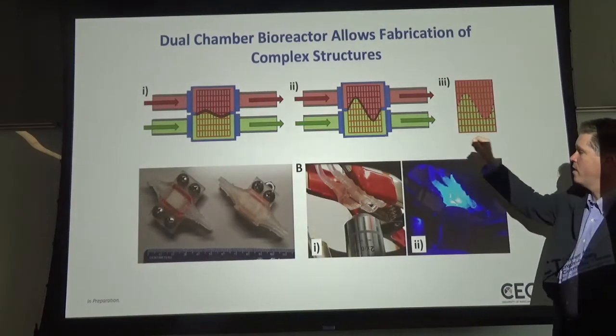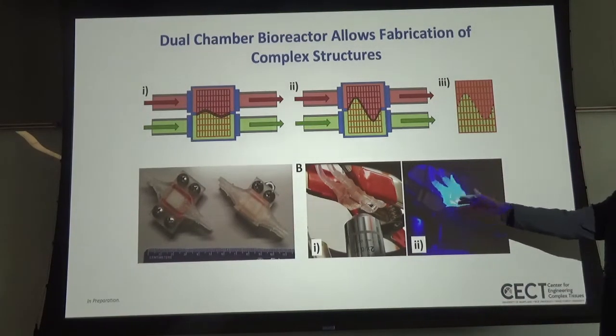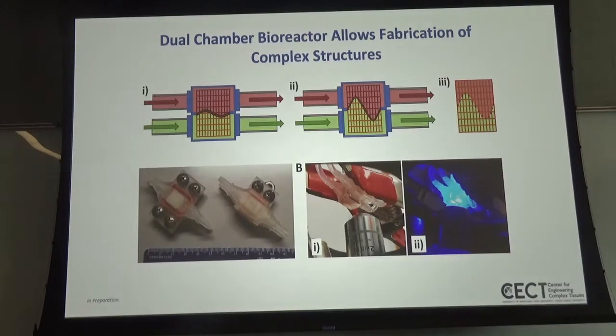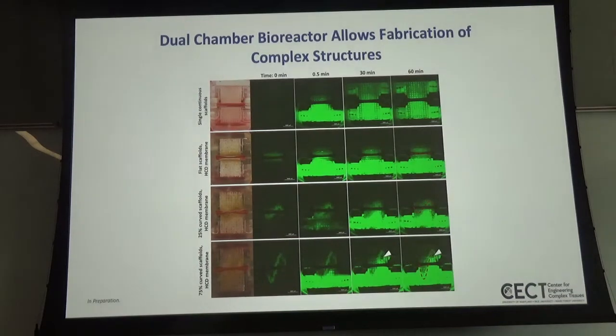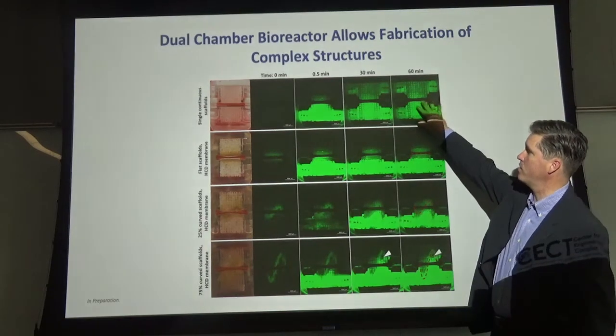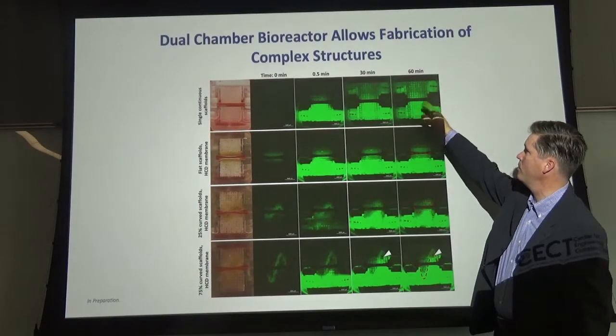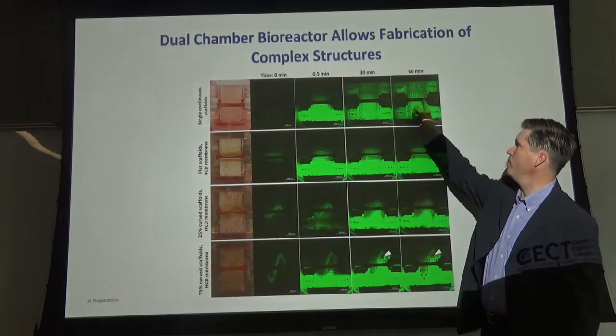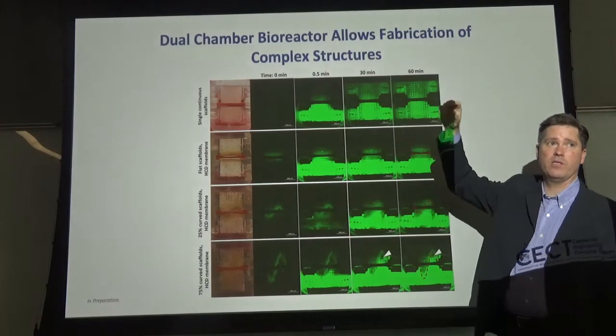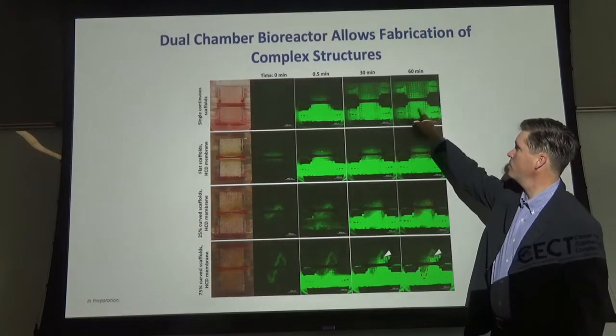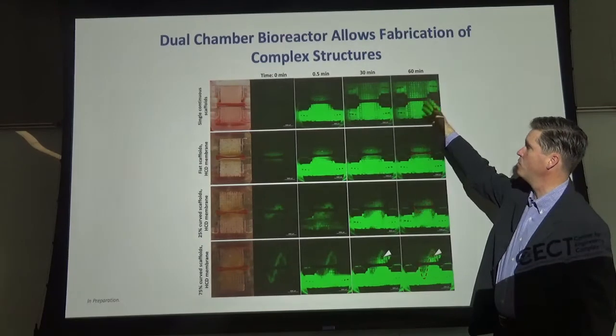So you can see the kind of design here, and then ultimately how it fit together in the bioreactors that he built. So this was an interesting spatial study where he's just using fluid dye to illuminate the bottom chamber, and did this as a function of membrane shape. So here you can see a single continuous scaffold with no membrane separating the upper and lower chamber. This is not the membrane, this is a rubber gasket that separates the two chambers. So here's a single continuous scaffold, and you see the dye diffusing across.